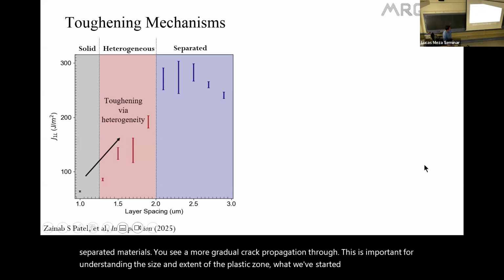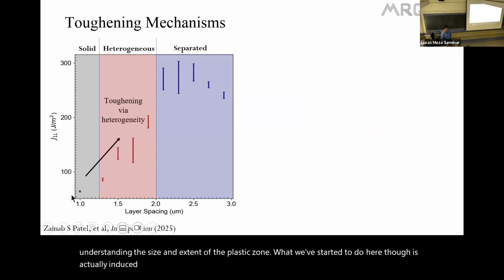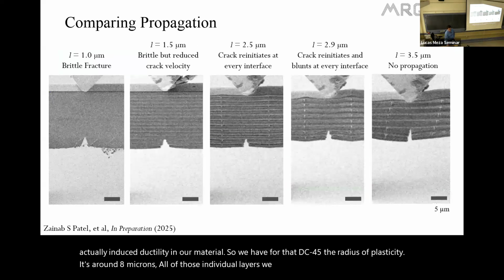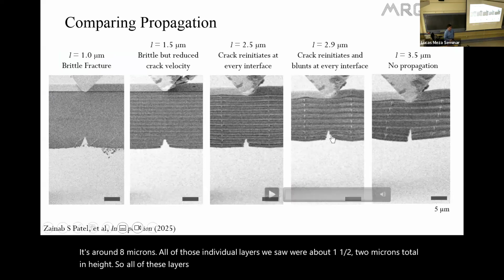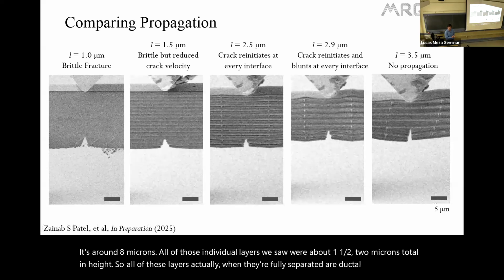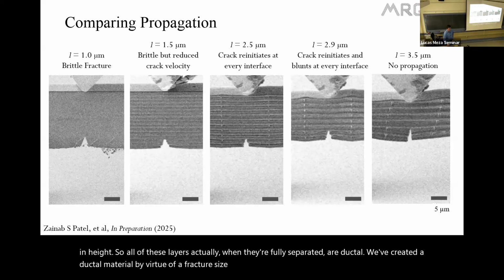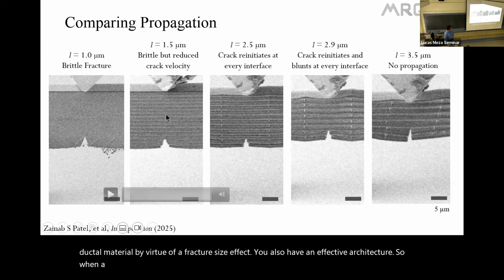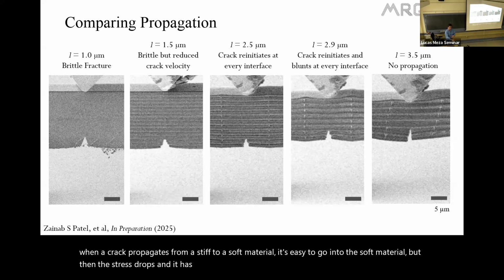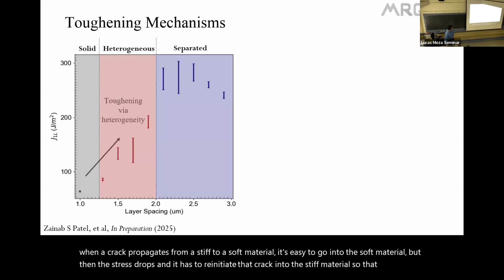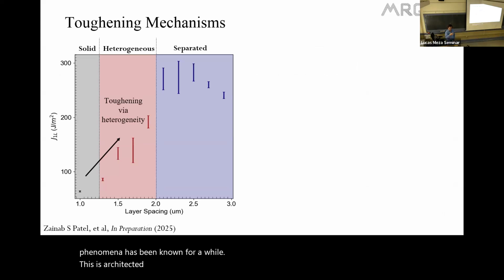What we've started to do here, though, is actually induced ductility in our material. So we have, for that DC45, the radius of plasticity is around 8 microns. All of those individual layers we saw were about 1.5, 2 microns total in height. So all of these layers, actually, when they're fully separated, are ductile. We've created a ductile material by virtue of a fracture size effect. You also have an effective architecture. So when a crack propagates from a stiff to a soft material, it's easy to go into the soft material, but then the stress drops and it has to reinitiate that crack into the stiff material. So that phenomenon has been known for a while. This is architected heterogeneity. So if you just take E1, E2, different materials, different stiffnesses, you get this sort of toughening effect.